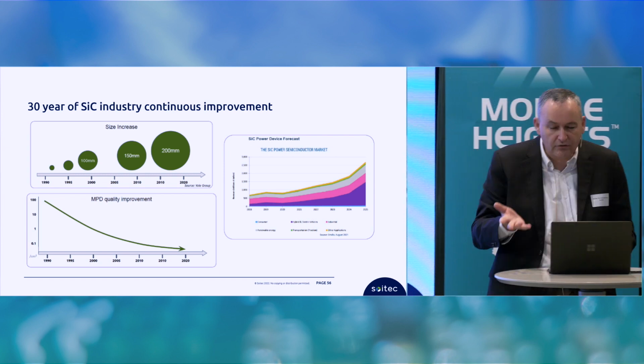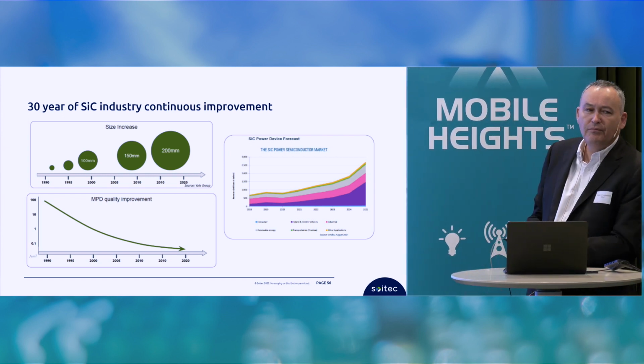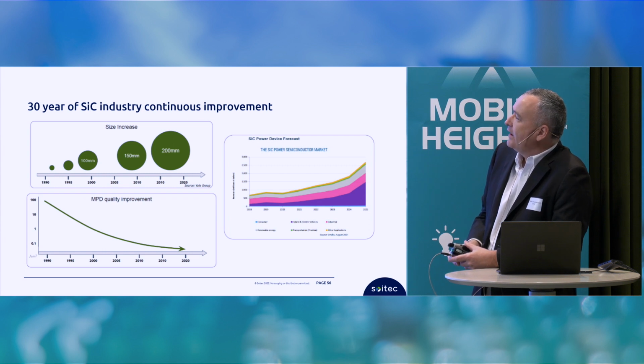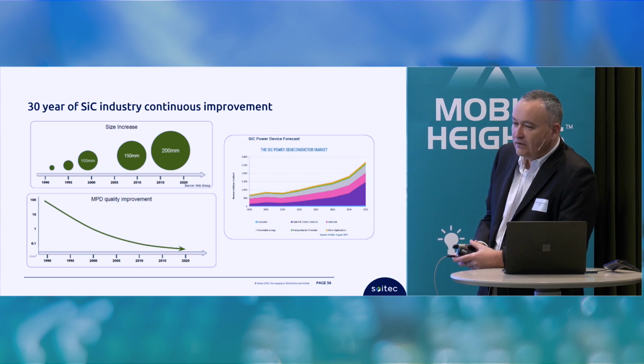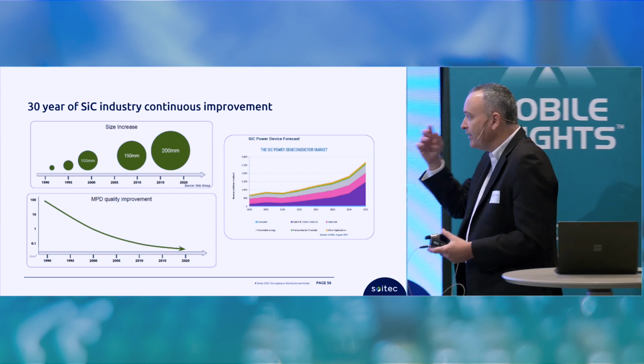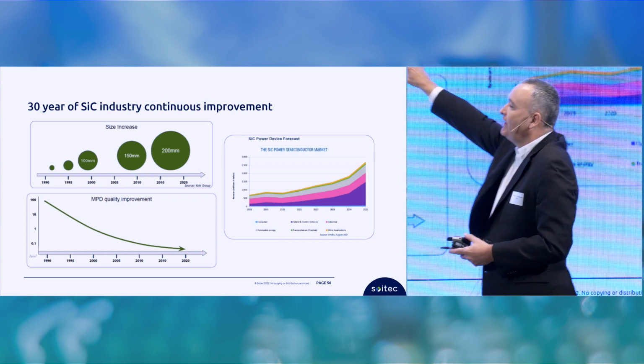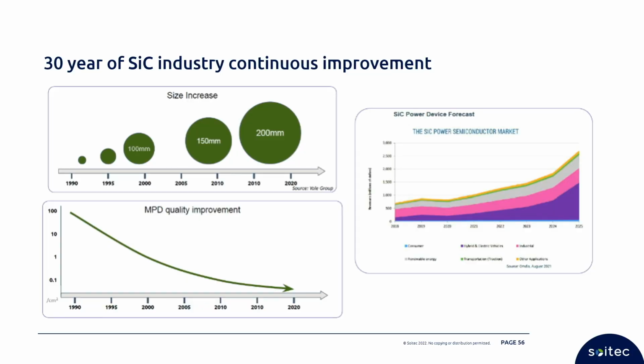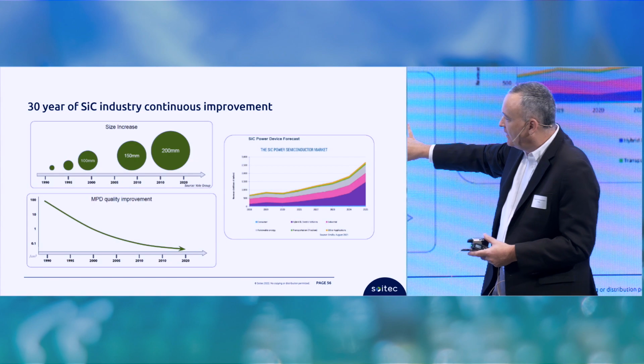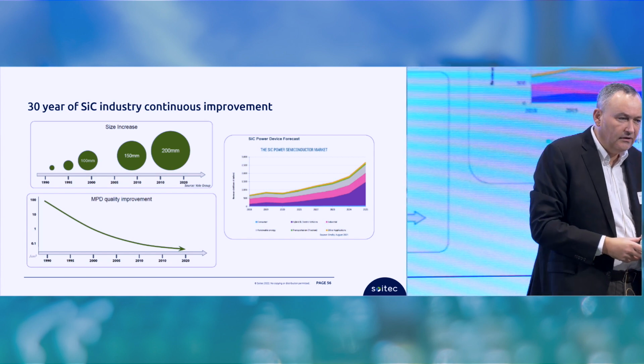Also, SiC materials is proposed to improve the power electronics performance. And for 30 years, the industry has already demonstrated a very significant improvement. One point for SiC materials is we increase the size of the materials. Three decades ago, it was a few tens of millimeters in diameter. Now we have 200 millimeters product. Also in quality, micropipe is an issue for device performance and device reliability, and we have had several decades of improvement in 30 years.